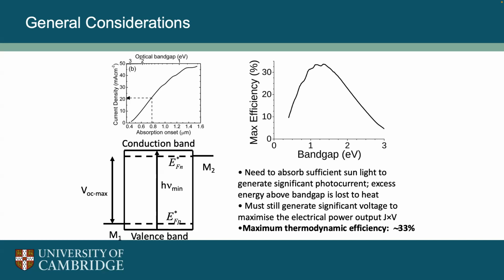So the microstructure I showed has two kinds of disorder. There's structural disorder, where as you move around, the crystal structure changes a bit. That seems to be problematic. There's another disorder, which is chemical disorder, and as you move across, there are chemical variations, for example, in the halide content. What we find is that this gives a little bit of band gap variation across the film, and so carriers can funnel down to the lowest band gap. And in those regions, they recombine very radiatively.